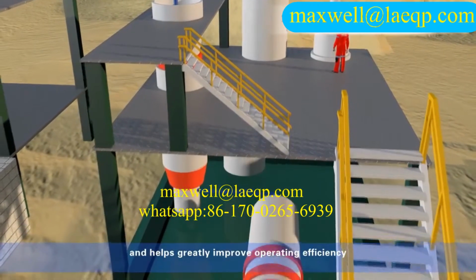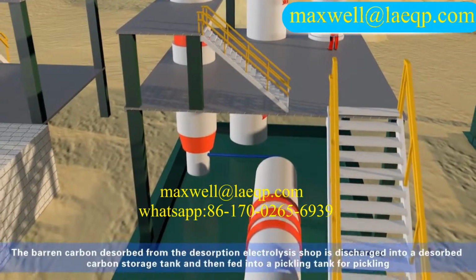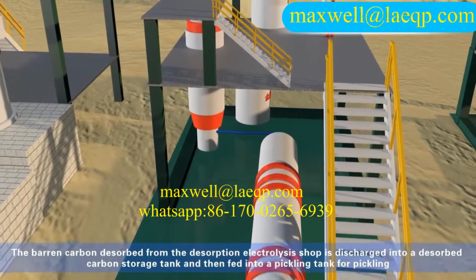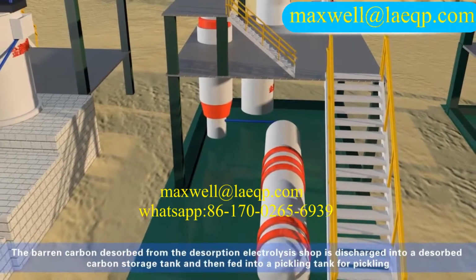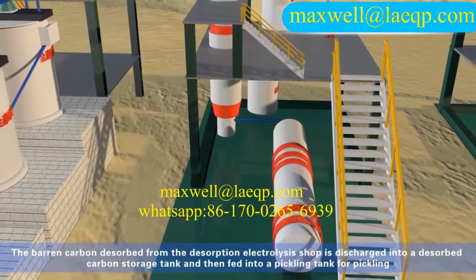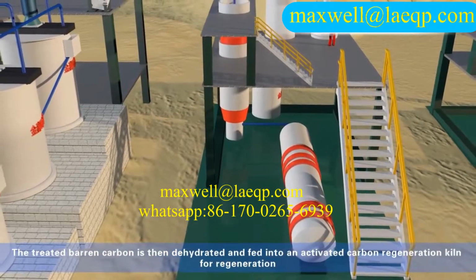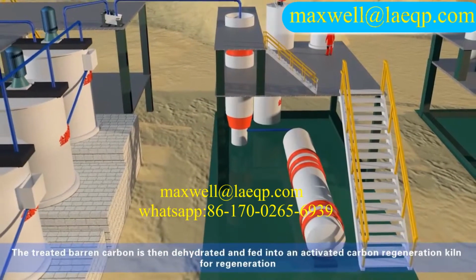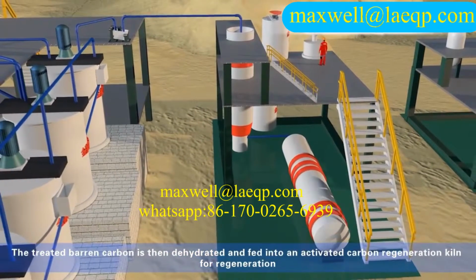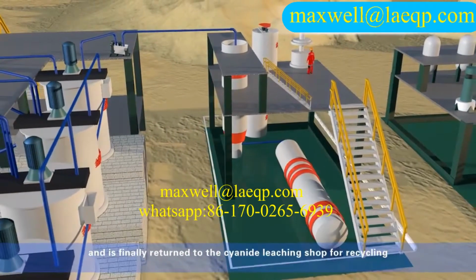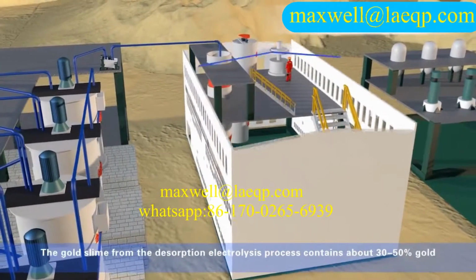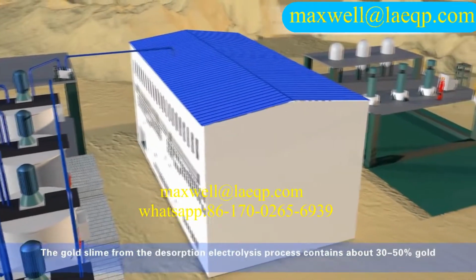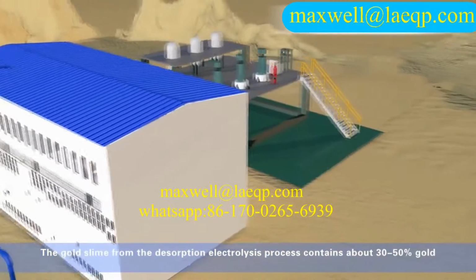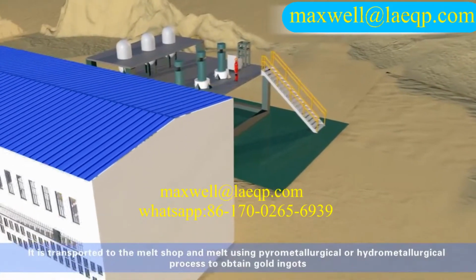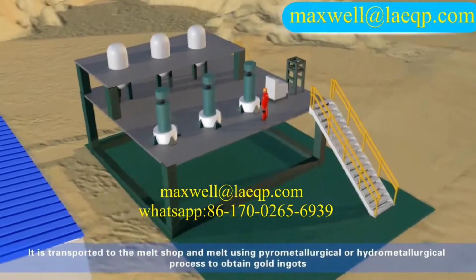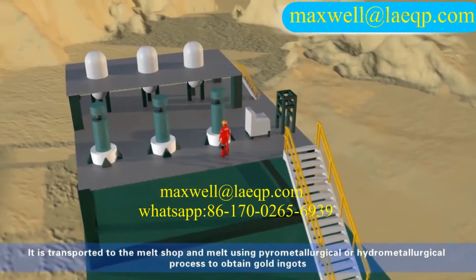The barren carbon desorbed from the desorption electrolysis shop is discharged into a desorbed carbon storage tank and then fed into a pickling tank for pickling. The treated barren carbon is then dehydrated and fed into an activated carbon regeneration kiln for regeneration, and is finally returned to the cyanide leaching shop for recycling. The gold slime from the desorption electrolysis process contains about 30 to 50% gold. It is transported to the melt shop and melted using pyrometallurgical or hydrometallurgical process to obtain gold ingots.